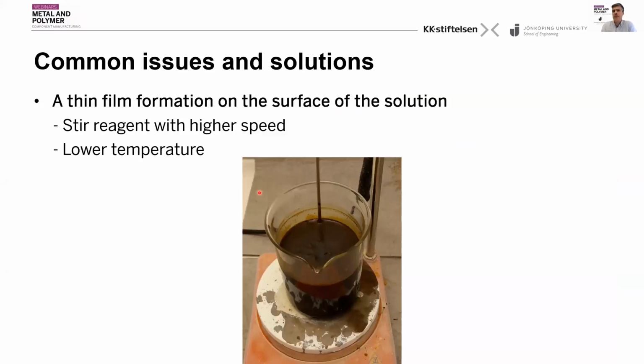The last problem that can occur during the etching process is that a thin film forms at the surface of the solution during the etching. And if this film is in contact with the etched surface, then it hinders the etching process. So it's something that we have to get rid of. It's unwanted impurities. So in order to get rid of this, we have to stir the reagent at higher speed. It's one of the solutions. And we can also reduce the etching temperature.